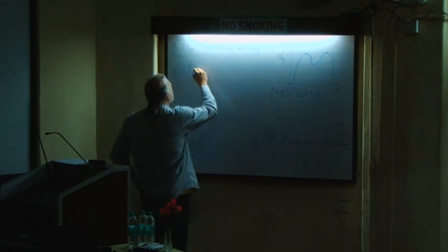So if I write this out, now you will see where this equipartition relation comes out useful. Gamma will be, so what is this? An integral over 1/2 k (dxm) squared. This is the gradient squared term. So this is non-zero in the interface solution, but it is 0 in the homogeneous solution. So here I do not need to subtract anything from this, because I have to subtract 0.